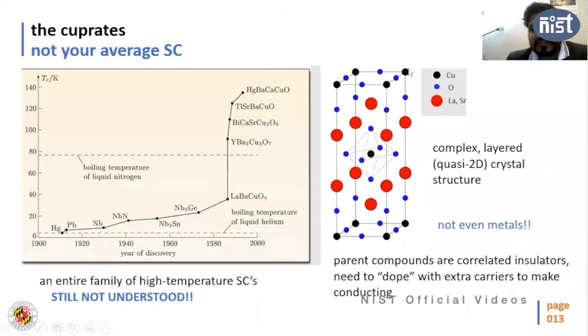Now, in terms of crystal structure, the main difference is that all these superconductors below this one more or less have a cubic crystal structure, but these superconductors have a tetragonal crystal structure. Now, the other thing is that everything in this material is happening only in this plane, this copper oxygen plane. So the resistivity, superconductivity, everything is controlled by this plane. And all these regions work like a charge reservoir.